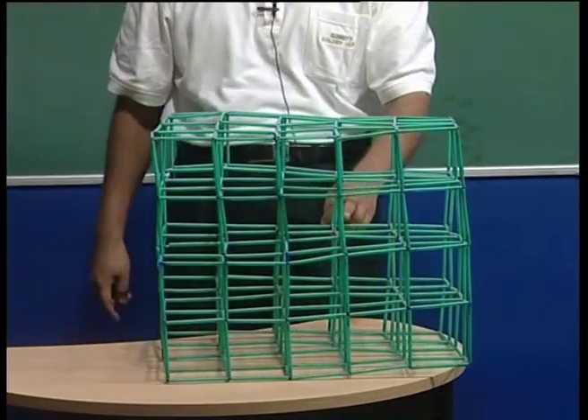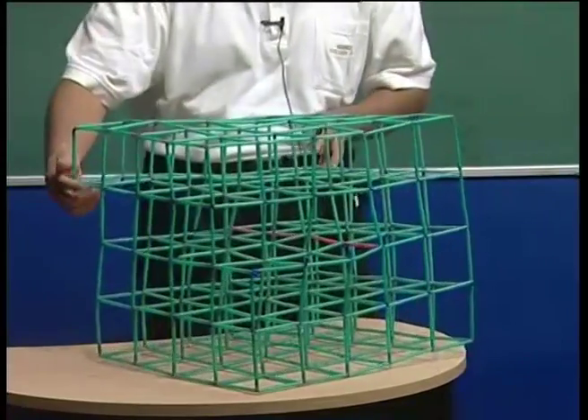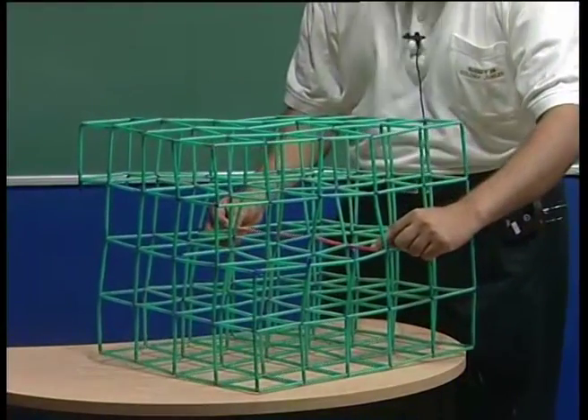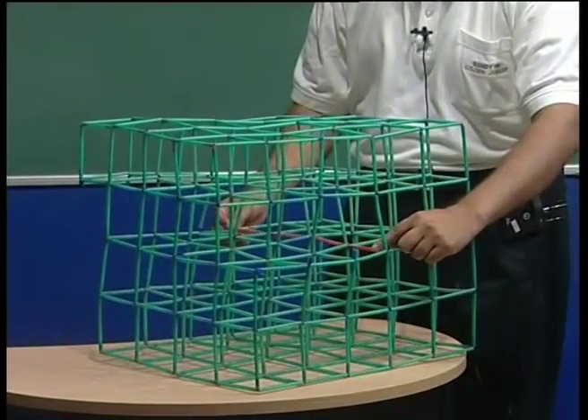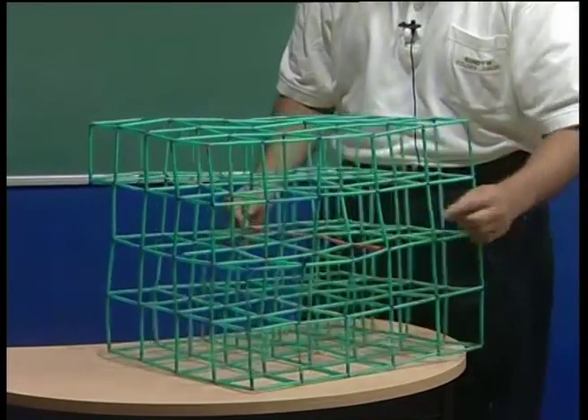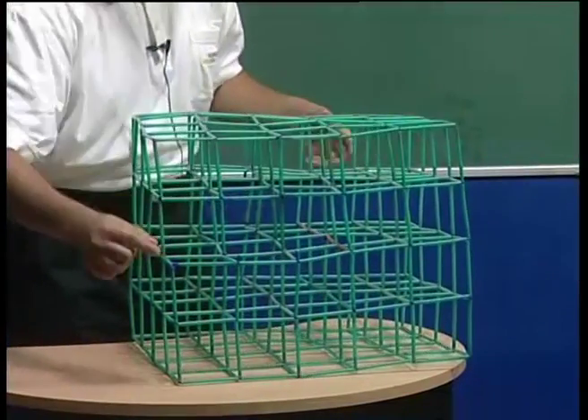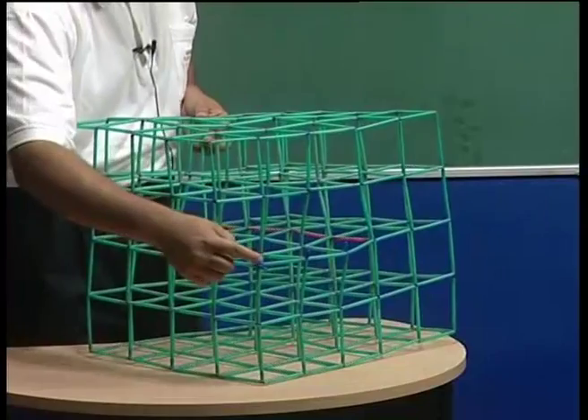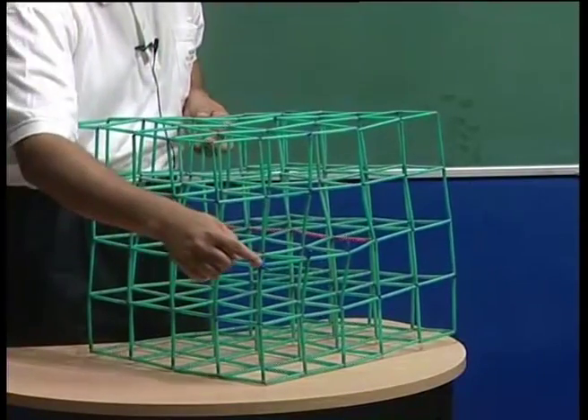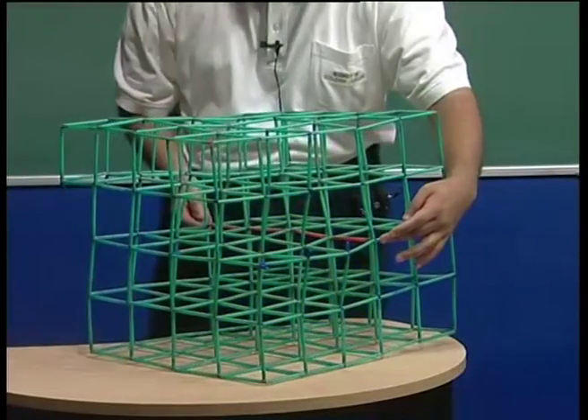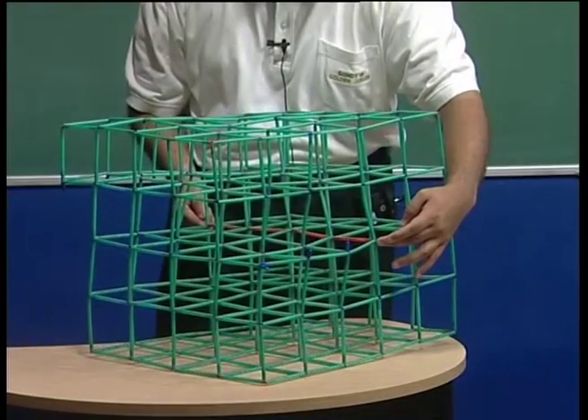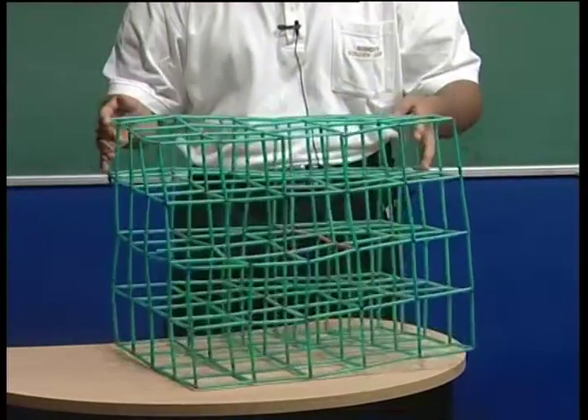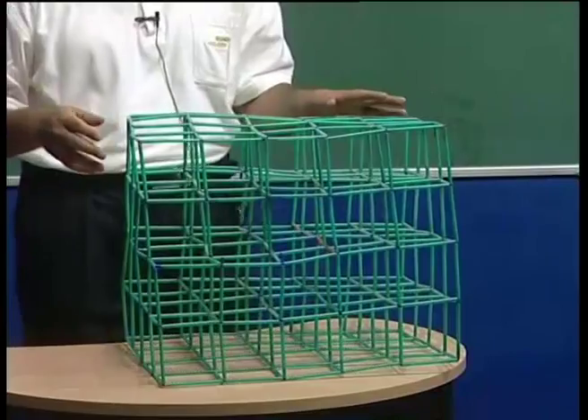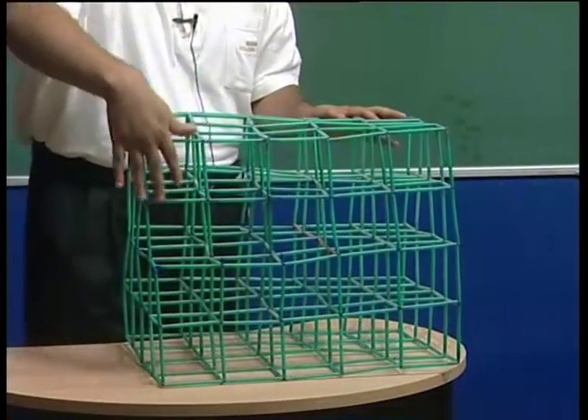Now, my dislocation line is this red line, which I can shift a little bit and show you. So, this is my red line here, which is the dislocation line, and this is my Burgers vector, B, which is also here. This point joining this point can be thought of as the Burgers vector, and therefore this Burgers vector is parallel to this dislocation line. If I look at my crystal again, you can see that these planes are bent, they are sheared.